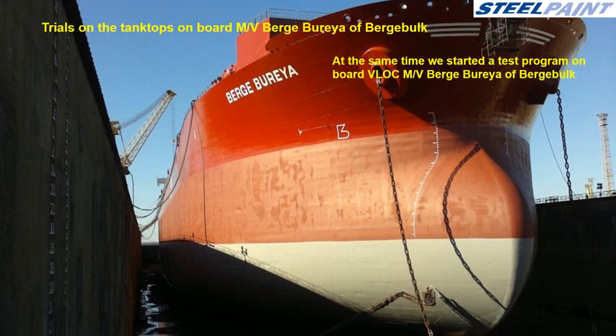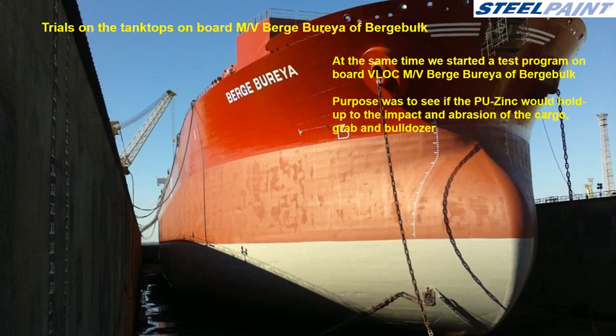At the same time, we started a test program on board VLOC Berge Bureya of Berge Bulk. The purpose of this test was to see if the PU zinc would hold up to the impact and abrasion of the cargo, grab and bulldozer, not only on the lower hopper and sides, but also on the tank tops. The total area of the test is about 100 square meters in the center and partly on the lower hopper, in hold number 6. The surface preparation was slurry blasting, SA2.